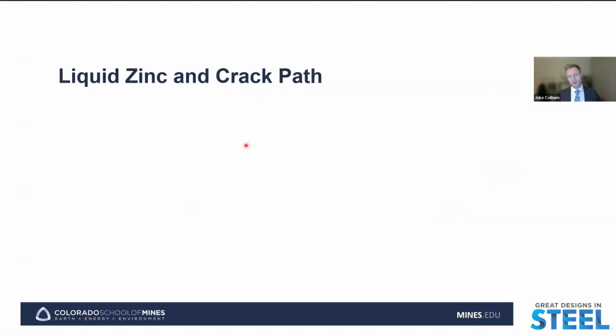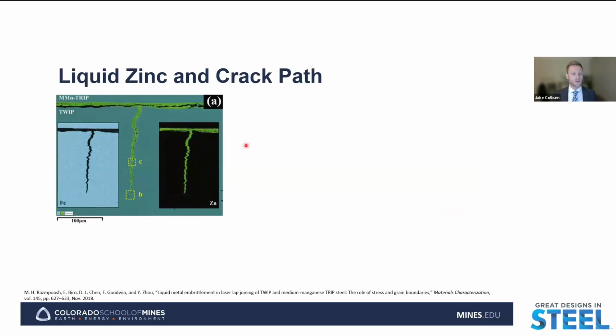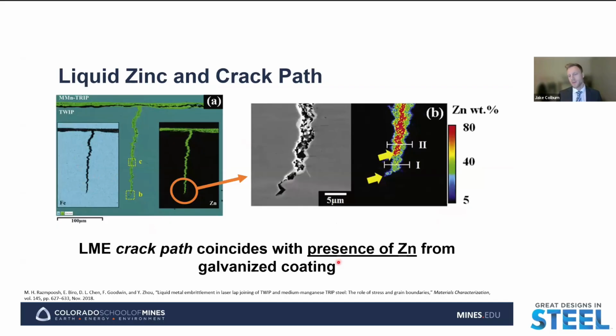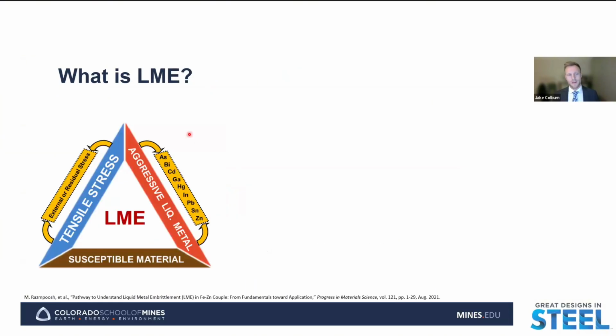Specifically for liquid metal embrittlement cracking, the cracks that form in the weld shoulder always coincide with the presence of zinc from the galvanized coating. This is one of the things hinting us towards the fundamental idea behind LME, liquid metal embrittlement cracking, because as we see these cracks, we can also see the presence and penetration of zinc from the coating along with them.